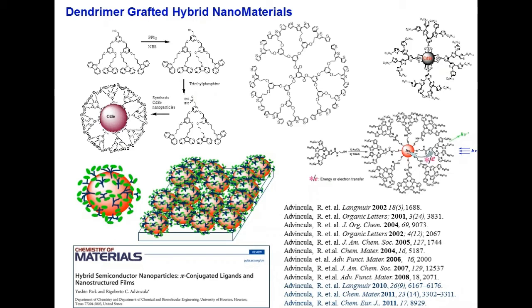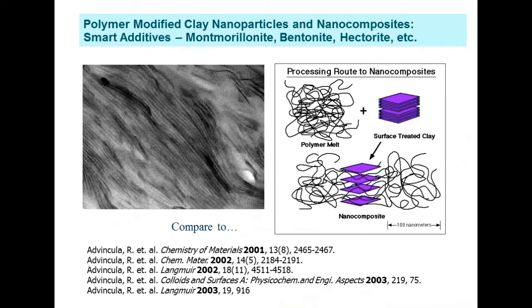types of display applications. Now, in the area of clay nanocomposites, one can functionalize clay and thereby change its ability to disperse or observe the percolation threshold to observe any thermomechanical improvements on the film property itself. And this is in comparison with the traditional method of incorporating clay, which is usually done by melt intercalation. So that means that surface functionalization is a way to work with clays like montmorillonite, bentonite, hectorite, laponite, or different synthetic clays that are actually used in many applications, including coatings and drilling fluids.